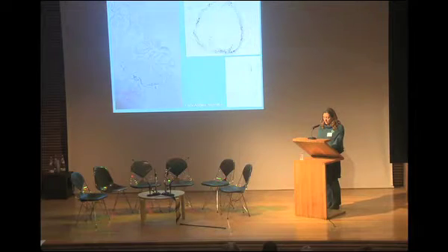The necklace media does not display signs of oxidation often associated with silver point, nor does it appear to be lead point under magnification. Whilst I'm aware that lead point is visible in infrared, the infrared carried out seems to further confirm that this is not a silver point drawing, since it remains visible. Moreover, Raman analysis of these areas showed a strong carbon signal.